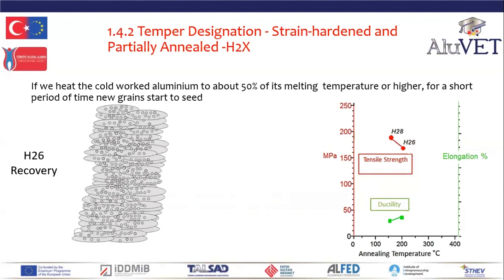If we heat the cold worked aluminium to about 50% of its melting temperature or higher, that is the recrystallization temperature, and hold at temperature for a short period of time, new grains start to grow. This is the H26 strain hardened, partially annealed, three-quarter hard condition. We have seeded the growth of new grains, so started the recrystallization process. Accompanying the start of the recrystallization, we see a slight reduction in strength and a corresponding increase in ductility.